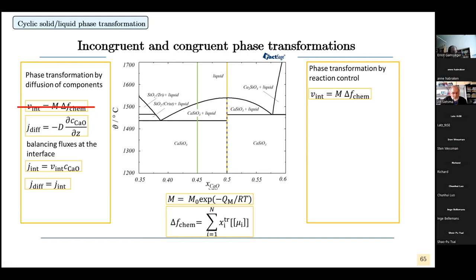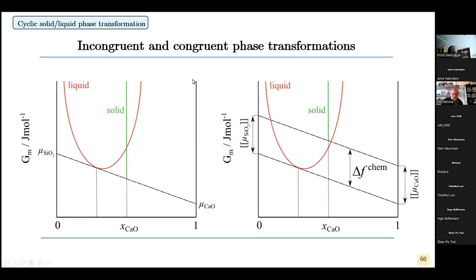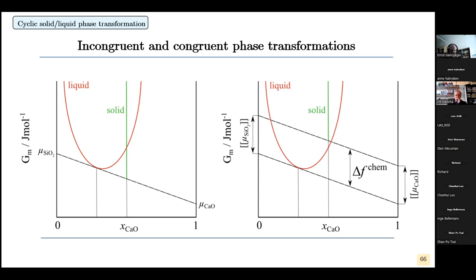In the case of congruent melting, the interface velocity is linearly related to the chemical driving force and of course no bulk diffusion is required. Here you can see the situation at the incongruent interface: the liquid phase, the solid phase, and the common tangent construction. In the case of the congruent phase transformation, we have the liquid phase and the solid with a parallel tangent construction for maximum dissipation. These parallel tangents come closer and closer until they are the same when global equilibrium is reached.